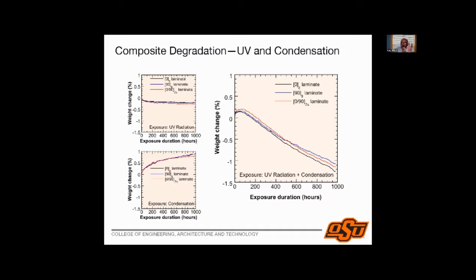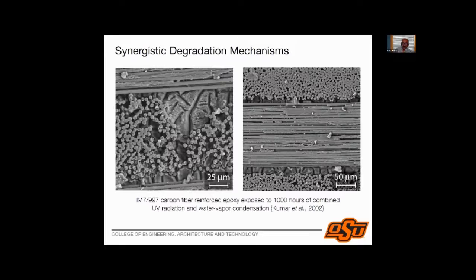So the reason I talk about this is that this was the first time that anybody had looked at two environments operating on composites to see what would be the long-term effects of that. And we were very surprised when we saw this. What we found was that if you have both these environments working at the same time, you actually cause physical damage to the composites. And this is work that first got us started into looking at synergistic degradation mechanisms, and it was published in 2002. So this is a historical paper for our group.